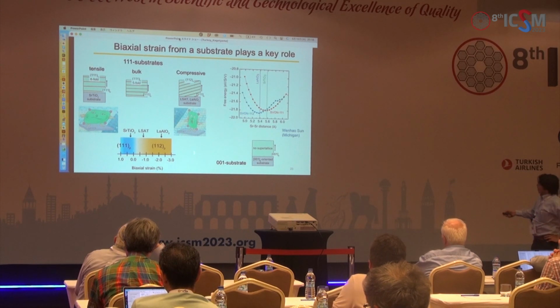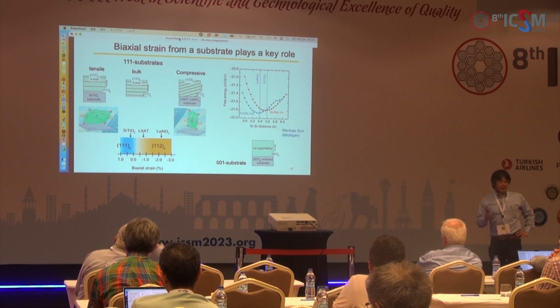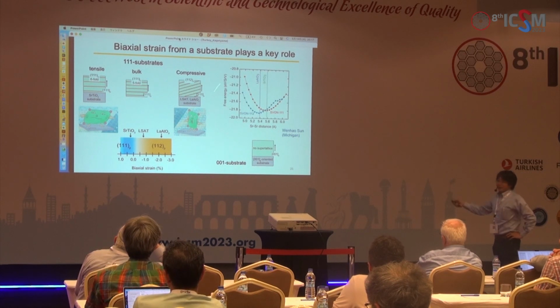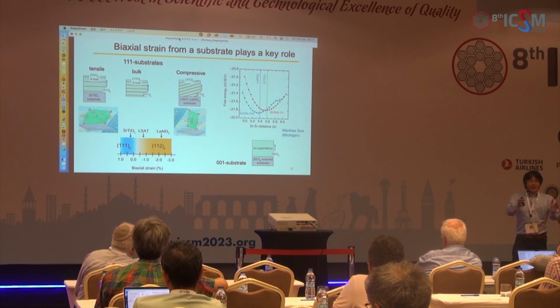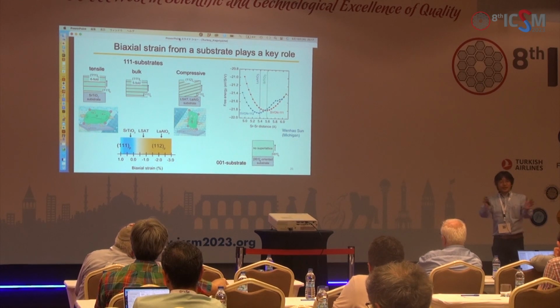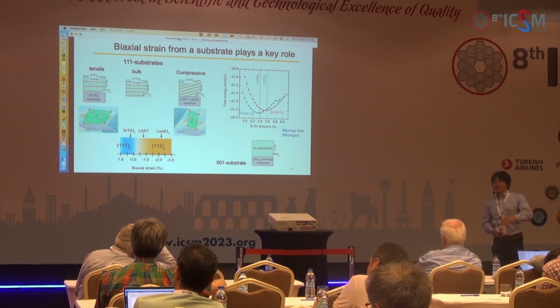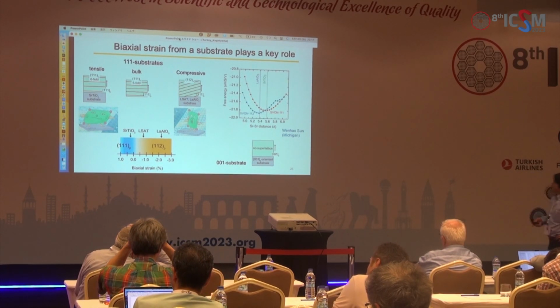And actually this strain effect was supported by DFT calculations. I collaborated with Ben Hobson, currently at Michigan University, and this calculation shows that applying strain obtains the superstructure, namely the oxygen vacancy ordering, is achieved.